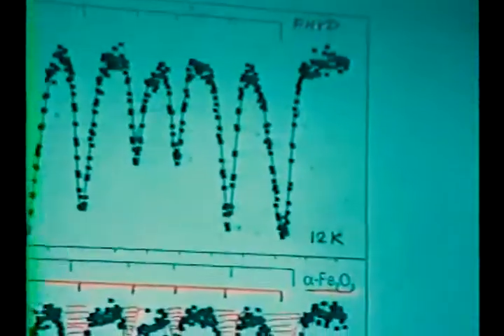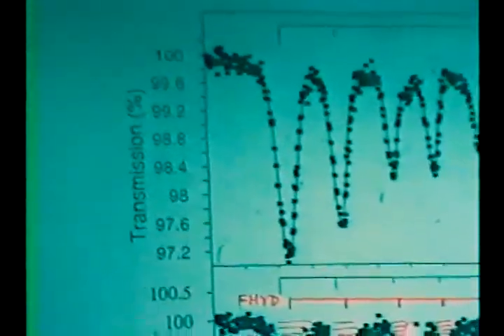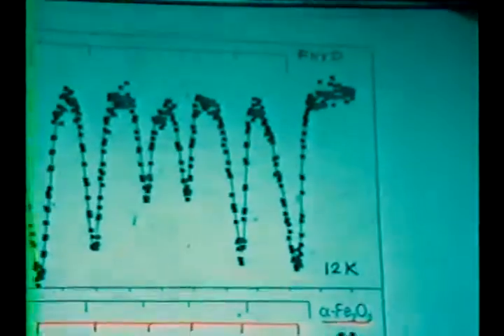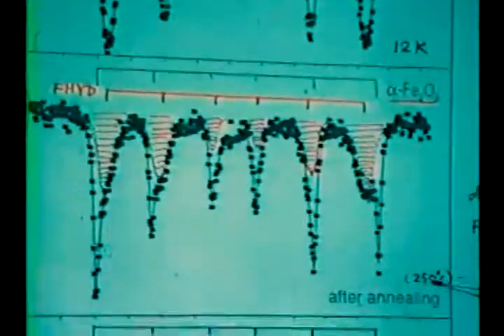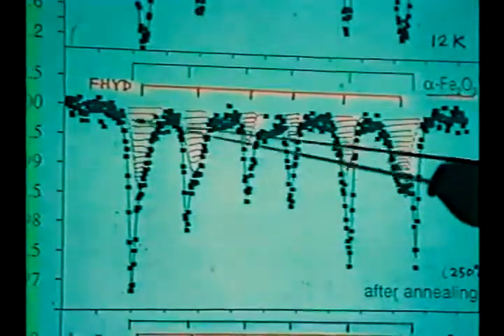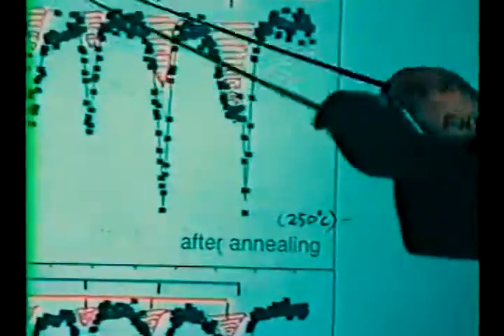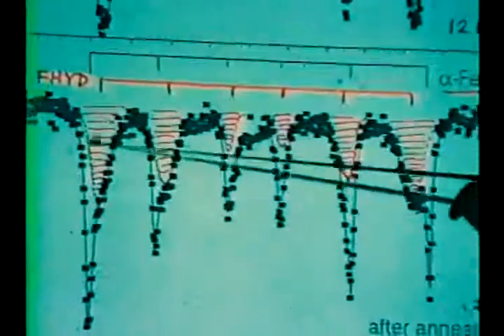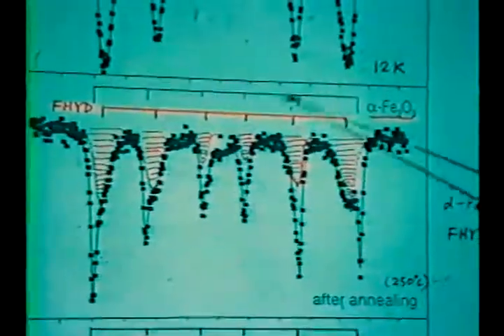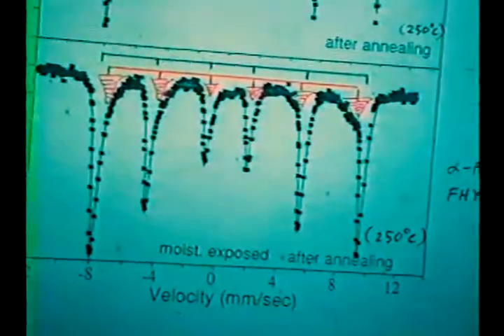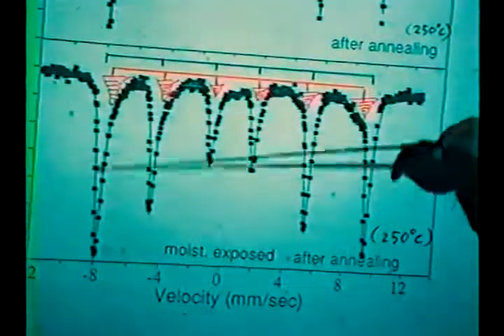If you look at the bulk, it gives a better result. On top this is ferrihydrite measured at 12K. After annealing at 250 C, you see basically two phases: the red one is ferrihydrite, and these sharp peaks represent hematite. But if the sample has been exposed to air, you see more hematite form.